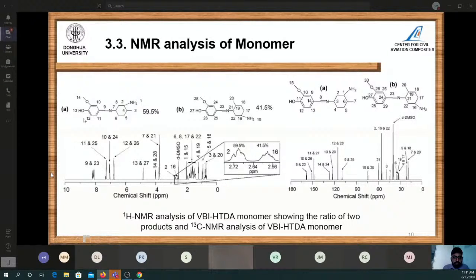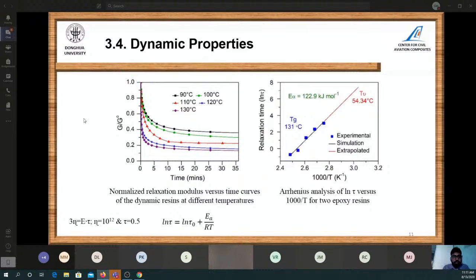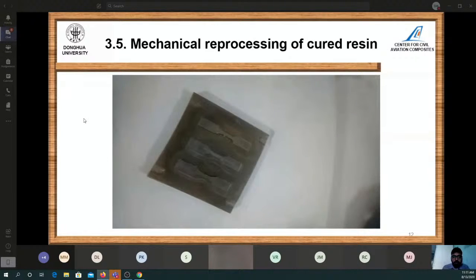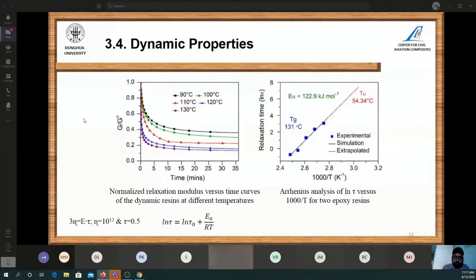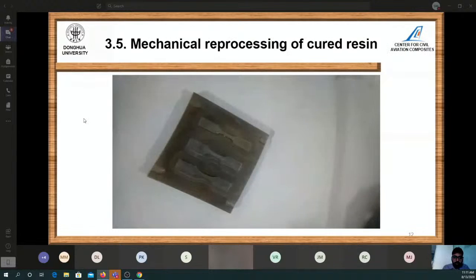We did the CNMR for this to guarantee the reaction has occurred, and then we assessed the dynamic properties of the cured coupon, that it has high activation energy as well as a high glass transition temperature, while the Vitrimer transition temperature was 54.34 degrees centigrade, but the glass transition is quite high, it's like 131 degrees centigrade. And this is the video that we also reprocessed to guarantee that it has self-healing properties. So we can refer to this video.